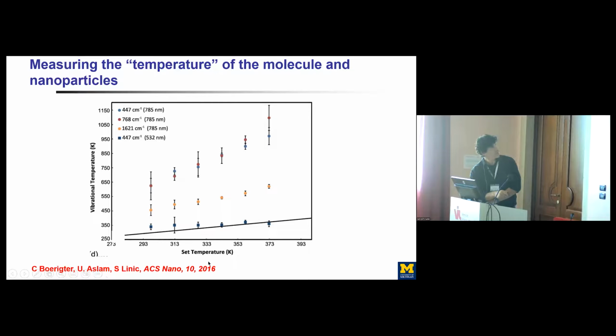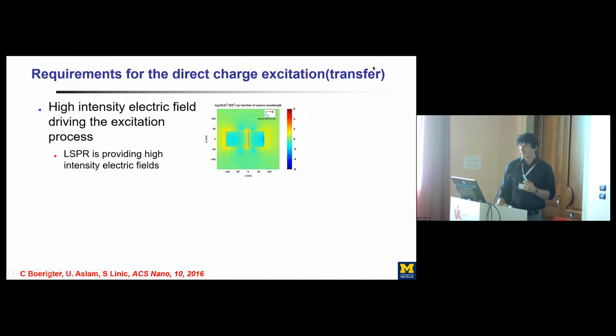And on the other hand, if we do this anti-Stokes to Stokes ratio to measure the temperature of the molecule itself under these conditions, and we do background of anti-Stokes to measure the temperature of the nanoparticle itself under the same conditions, we actually see situations where the molecule is at a significantly higher temperature compared to the nanoparticle itself. So this is telling us that the energy is going through this low heat capacity molecule, and it's getting heated relative to the nanoparticle itself.